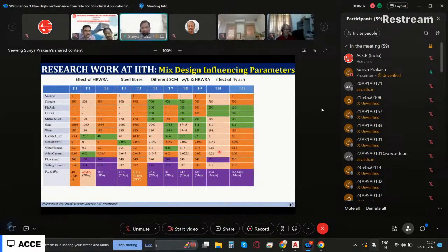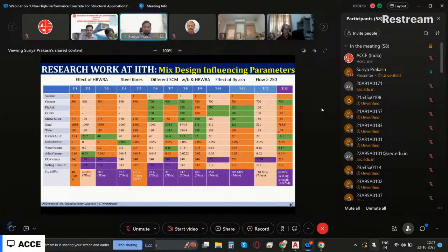So again, effect of fly ash. You see, finally we were able to get this mix at about 7 days. We were able to achieve about 110 megapascal, with a lower cement content of about 700 kg per meter cube. So like that, we have to do a lot of trials, and using the particle packing method there is an approach called the Andreasen model. If you know the particle size distribution of all the particles, then you can get the combined gradation. And with that, we can get an idea how good your mix design is. So this is how we have done it.